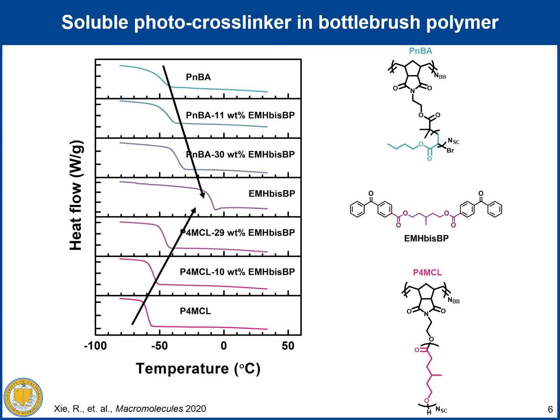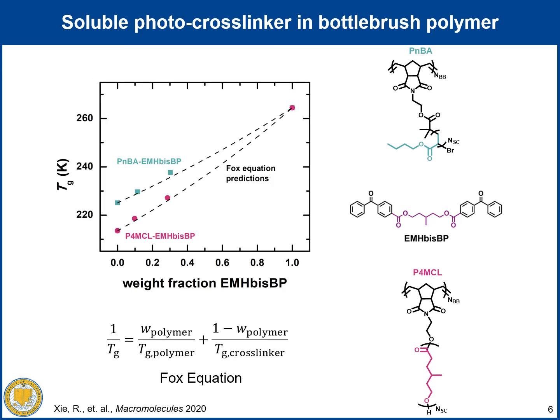Then we can confirm the amount of the shift in Tg actually follows the expected Fox equation very well for both mixtures. And also I will point out that only 2 weight percent of crosslinker loading or less is actually sufficient to form a robust and super soft network in the actual UV curing test that I will show you next.